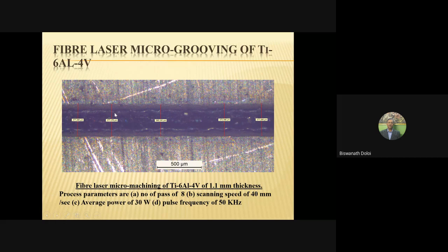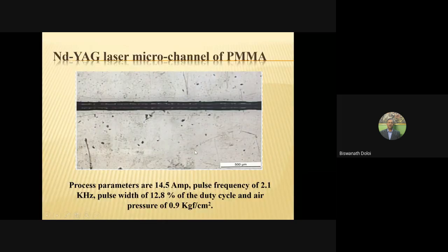In our laboratory we have done a lot of experiments to produce micro grooves, with size less than 500 micron, on Ti6Al4V by fiber laser. Average power is 30 watt, pulse frequency 50 kilohertz, and number of passes 8. Here scanning speed is very high: the cutting speed is 40 millimeter per second, and the thickness of the workpiece material is 1.1 mm, a Ti6Al4V sheet.